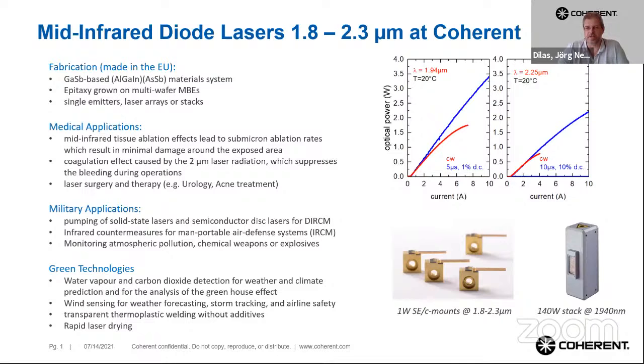The single emitters are often used also in pulsed mode. And in the upper right, you could see the power levels we achieve. Red is CW, so like 1.5 watts, and at 2.2 micron, it's more like 750 milliwatts. But in pulsed operation, it actually can go like a factor of 2 to 3 higher.